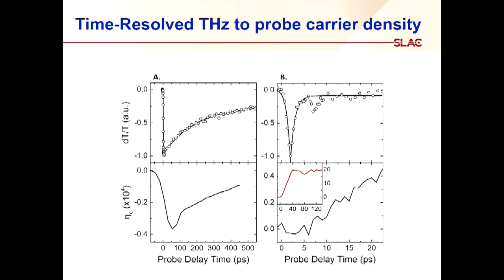we produce carriers, and then through radiative and non-radiative decay channels, the carriers go away. In rhenium disulfide, there are many, many more defects and so forth. So you produce carriers, but they go away very quickly. On the time scale, if you notice, a different time scale here, about one picosecond. So here they last for hundreds of picoseconds. Here they last for maybe one picosecond.